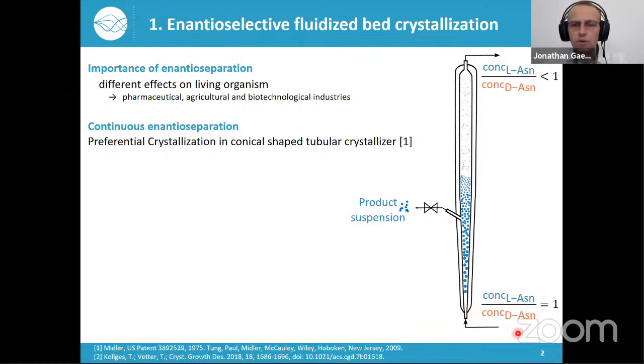We are starting from a solution with racemic composition. That means that our L-asparagine and D-asparagine have equal amount and equal concentration. And we are pumping this racemic solution continuously from the bottom through our crystallizer. By cooling, we create some supersaturation. And then we seed the process with crystals of just one enantiomer, our target enantiomer, for example now the L-asparagine. Then these L-asparagine crystals will start to grow and thus selectively remove just our target enantiomer from the feeding solution. So what are the advantages of using these tubular crystallizers?